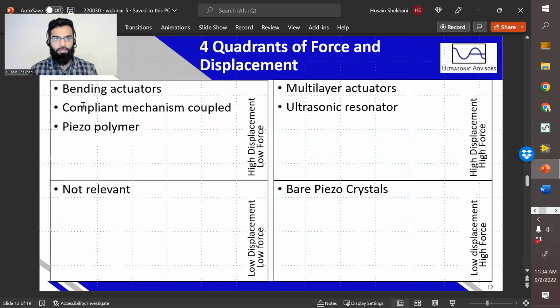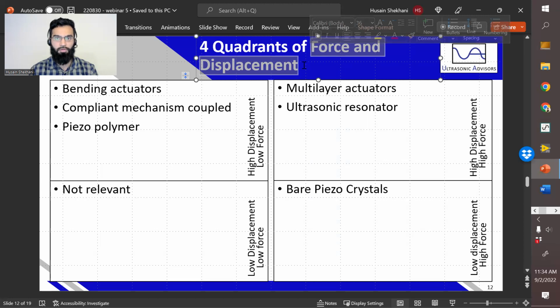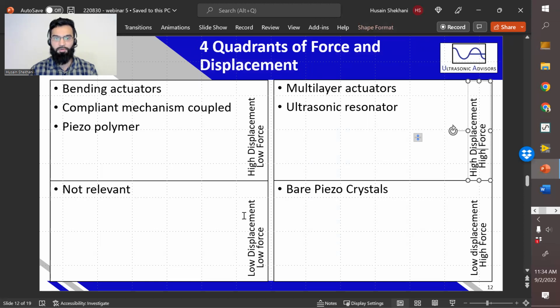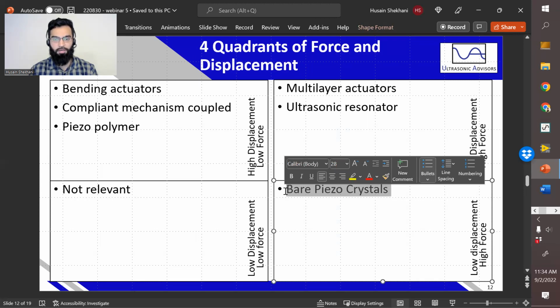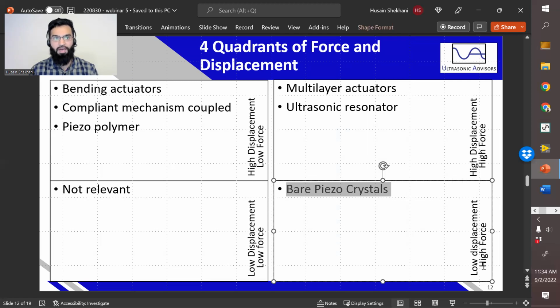Now I'd like to introduce another way of arranging our piezoelectric actuators. Force and displacement are the two things we look for when we talk about actuators. So in this corner, we have high force, high displacement. In this corner, we have low force, low displacement. And low force, low displacement is not really relevant for this case, because bare piezo crystals start with very low displacement, as I mentioned. They start with 0.4 microns by putting 1,000 volts on them, but they have very high force.